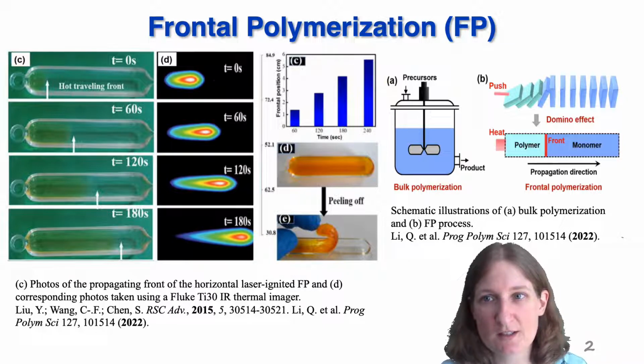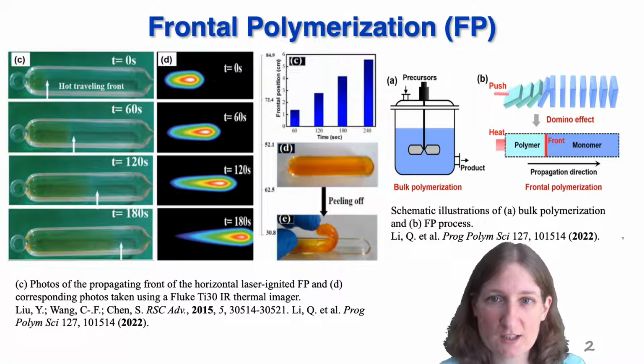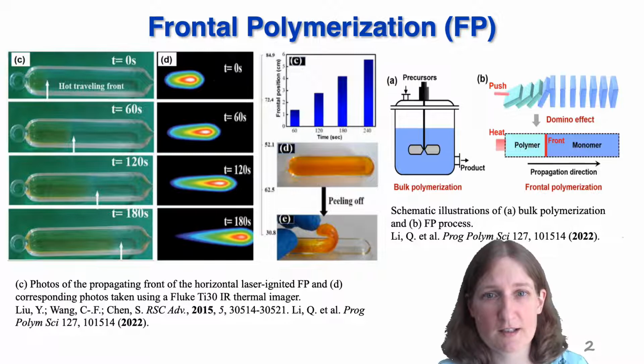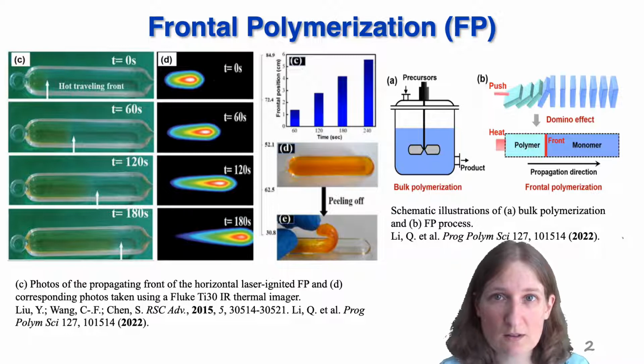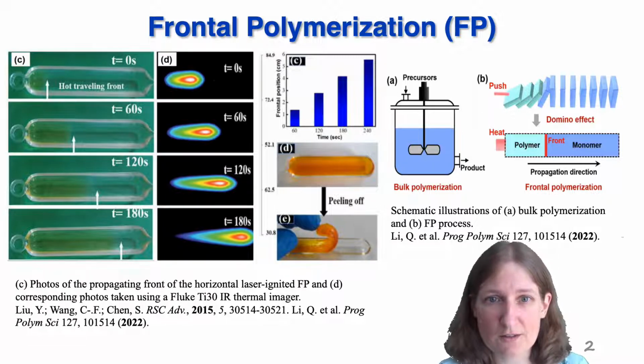Frontal polymerization is a simple, rapid, efficient, and green methodology for obtaining different polymeric materials such as resin, nanocomposite, interpenetrating polymer networks, and hydrogels. It consists of a radical polymerization with a radical initiator promoted by an energy source in the form of heat, UV light, infrared laser, ultrasound, plasma, etc. A self-propagating polymerization front disseminates throughout the monomer solution.